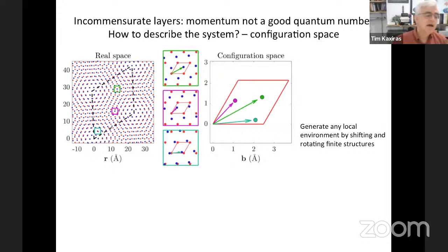And one very efficient way that we have found is to use what we call configuration space. So this is shown here schematically. These are two real space lattices. Blue and red are again the positions of atoms in the two lattices, and you see the different local configurations.